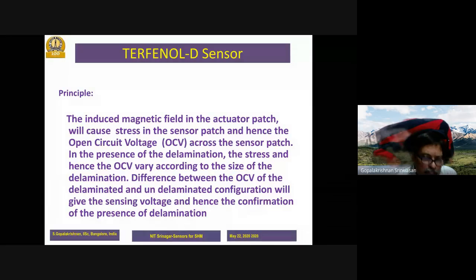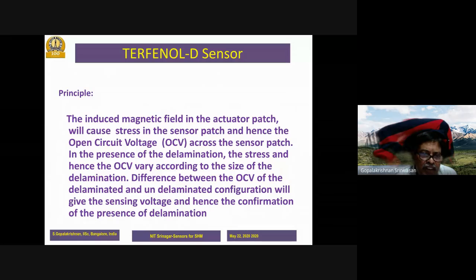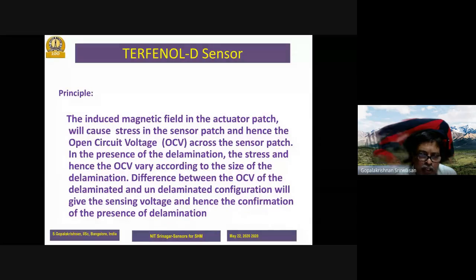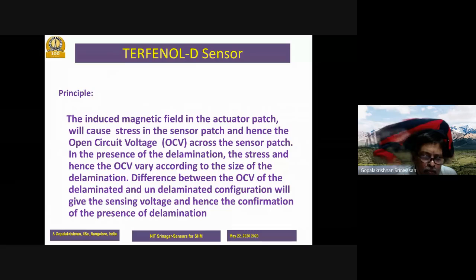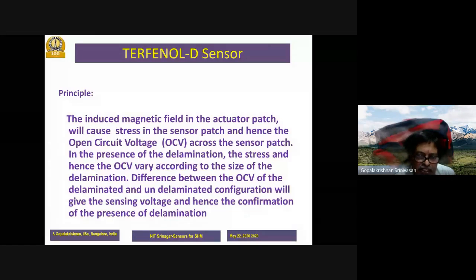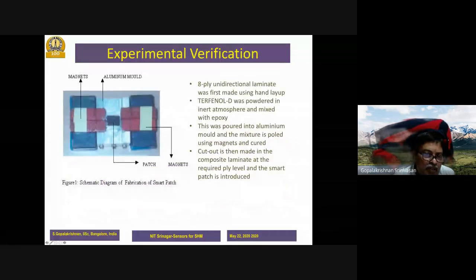So the principle here is the magnetic field induced in the actuator patch will cause a stress in the sensor patch, and hence the open circuit voltage changes. If the open circuit voltage doesn't change, then there is no damage. If it changes, it indicates the presence of a delamination or a crack. And using this, we can quantify the level of damage that is there. So this is how we made it.